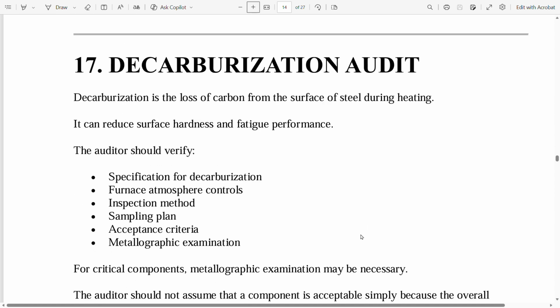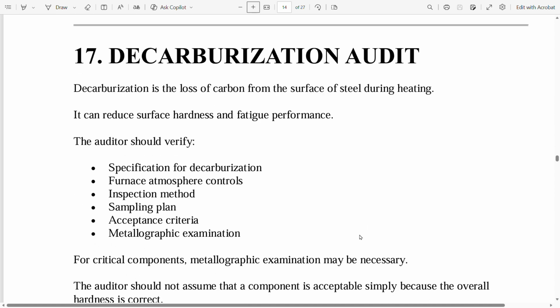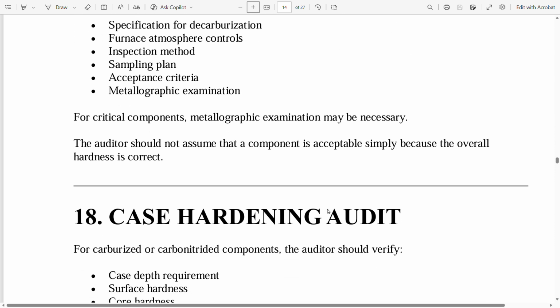Then 17th, decarburization audit. Decarburization is the loss of carbon from the surface of steel during heating. It can reduce surface hardness and fatigue performance. The auditor should verify specification for decarburization, furnace atmosphere controls, inspection method, sampling plan, acceptance criteria, metallographic examination. For critical components, metallographic examination may be necessary. The auditor should not assume that a component is acceptable simply because the overall hardness is correct.